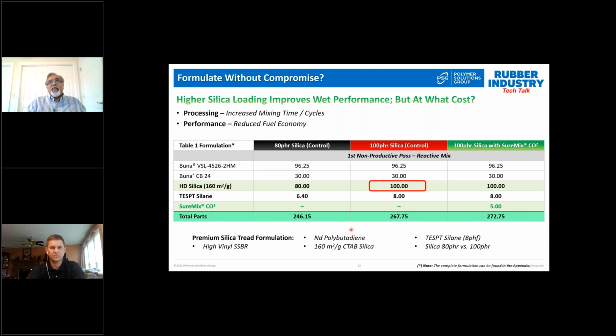But there are problems. It's difficult to mix 100 or 120 or 140 phr of silica. The viscosity of the compound increases significantly. There's also a performance penalty. As you increase silica, you also increase hysteresis. So how do we address that? We took the formulation which had 100 phr of silica and added 5 phr of SureMix. On the next slides, Aaron will walk you through the property changes on the processing side and then on the performance of the compound.